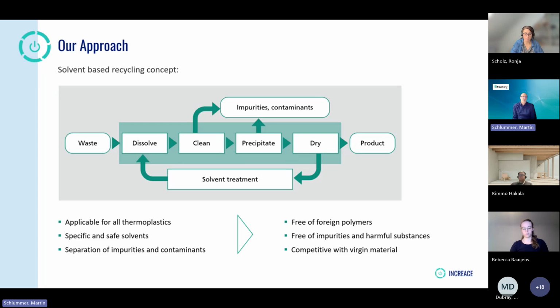And in the downstream cleaning process, we separate first the undissolved matter by sieves and others. And in the second step, we can even separate co-dissolved material. Co-dissolved material can be additives like flame retardants and others, which are simply extractively eliminated from the polymer solution. And in the end, after cleaning, we precipitate the material, we dry it. In this process, all the solvent is recovered and reused in the process.